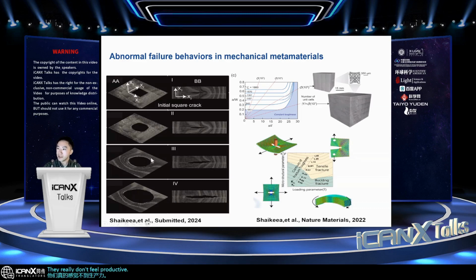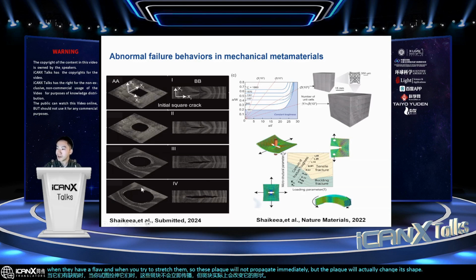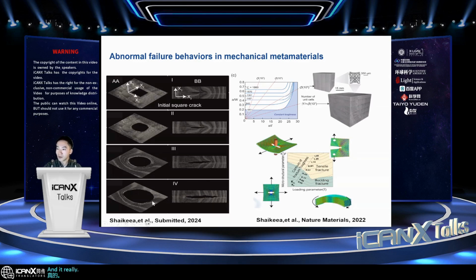They experience an R-curve behavior, which is similar to the bone in our body or a biomaterial. With a biomaterial, when it has a flaw and you try to stretch it, the crack will not propagate immediately, but will actually change its shape and display really ductile behavior.